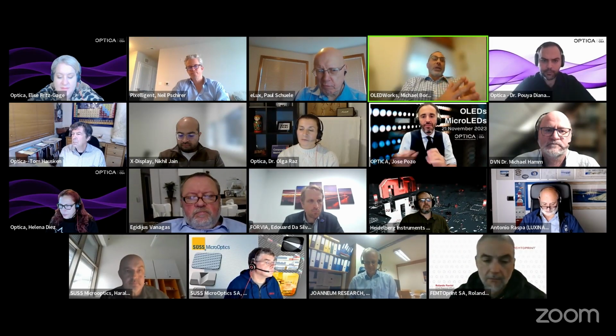Oh, okay. Thank you. So for organic LEDs, for OLEDs, they're very sensitive to moisture, and so we do need to protect them from moisture. So for applications that are, I'd say, either lower cost or extremely long lifetime, glass is definitely the preferred substrate. But obviously plastic provides some special benefits, even finer curvature, bending and unbending. And for some applications where extremely long lifetime isn't required, like cell phones or other limited use time applications, or where cost is not as sensitive, like it is in, let's say, automotive, then plastic is definitely a viable option and has a place.